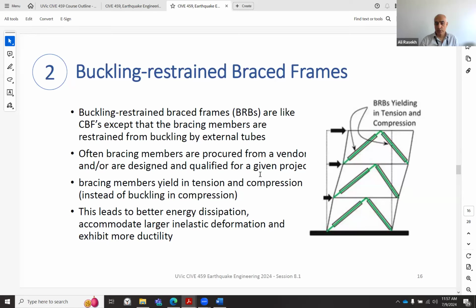Often bracing members are procured from a vendor. They are not really constructed in place because it's difficult to analyze and design to prevent buckling. A vendor has done that, and they sell the pre-tested braces, and it should be tested as well. Sometimes analysis is not good enough, so they do the test. They make sure that no buckling happens with that sleeve. Bracing members yield in tension and compression instead of buckling in compression. This leads to better energy dissipation, accommodates larger inelastic deformation, and these structures are considered more ductile.